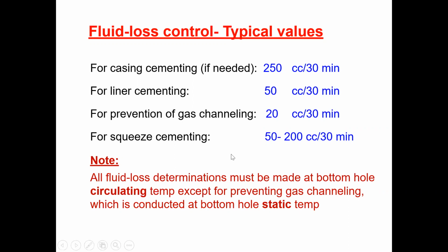I have also mentioned all fluid loss determination must be made at the bottom hole circulating temperature, except for preventing gas channeling, which is conducted at bottom hole static temperature. Remember, this is a very important point.